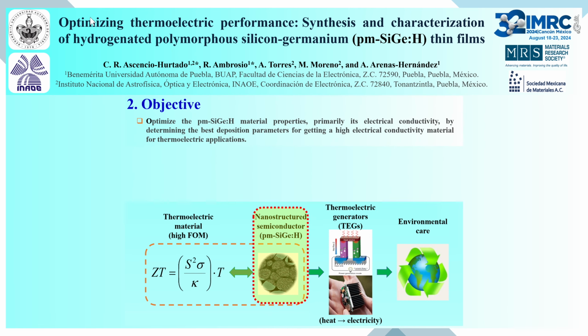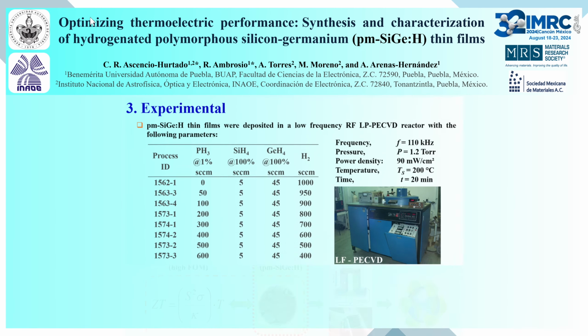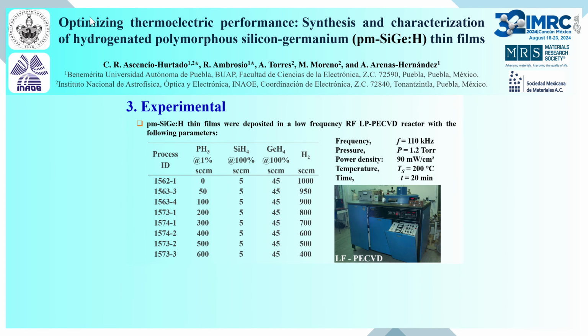Objective: to optimize the hydrogenated polymorphous silicon-germanium material properties, primarily its electrical conductivity, by determining the best deposition parameters for getting a high electrical conductivity material for thermoelectric applications. Experimental stage: polymorphous silicon-germanium samples were deposited by low-frequency PECVD.